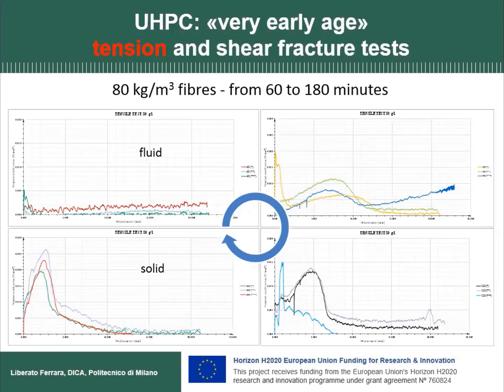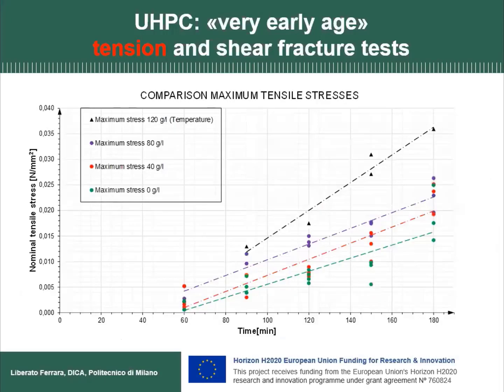And the same happens for the mix with 80 kilos. This is just an example, a mix with 80 kilos per cubic meter of fibers. You can also see how 80 kilos is surely still not strain hardening this material. These are direct tensile tests, but there is a significant post-peak toughness compared to the matrix.